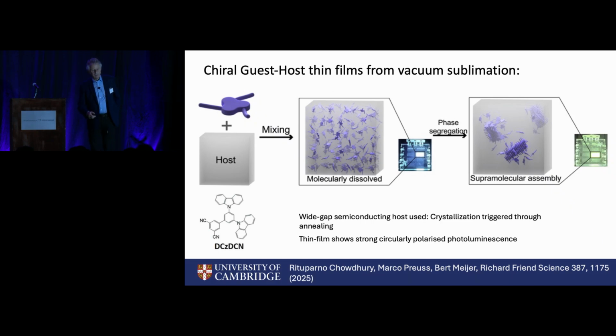So the surprise discovery is that if we try and make organic LEDs, which usually involves putting the emitter into a host that transports carriers but is a wide gap, a strange thing happens. As we co-sublime in the middle of the panel, we get isolated molecules. They emit blue, but with a little bit of heat treatment or passing electrical current through, we get a local crystallization within this high Tg matrix, and locally we get little chiral regions, and as they form, the luminescence switches from blue to green.